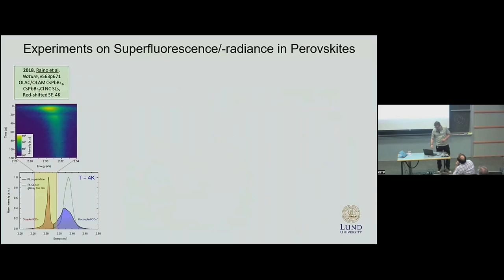So let's look at the state of the art - experiments on superfluorescence in perovskite. The field, I would say, was opened by the work from Maxim's group in 2018, where they observed interesting peculiar redshifts at low temperature in the nanocrystal superlattices of cesium lead bromide 3, with oscillating and very fast decays in the time domain. Since then...